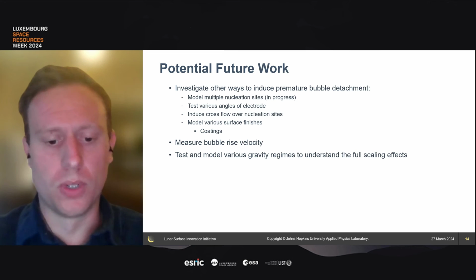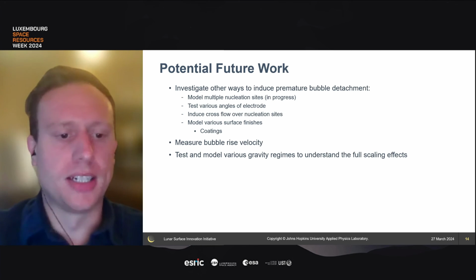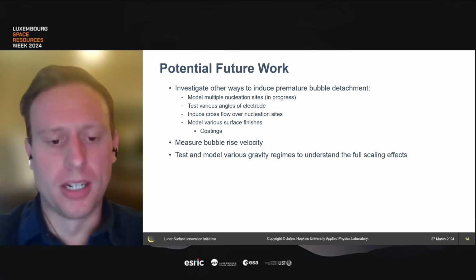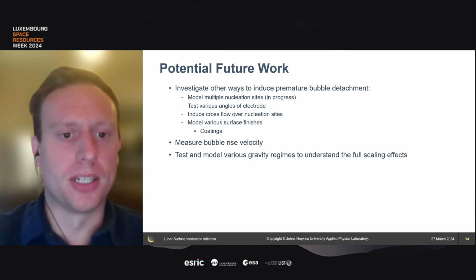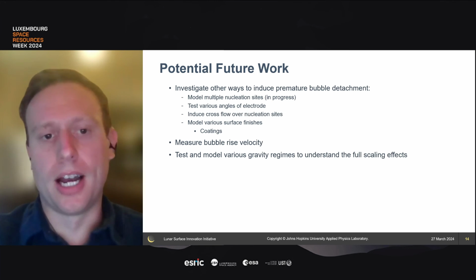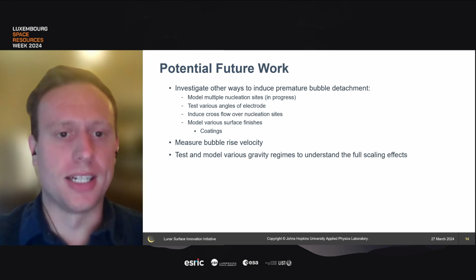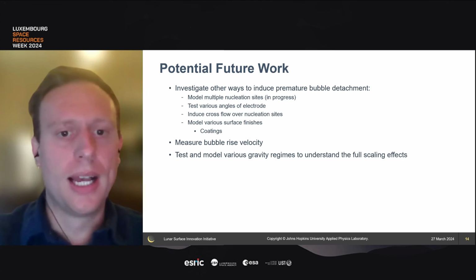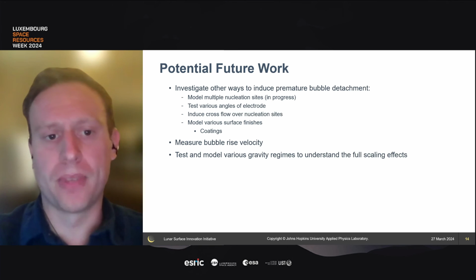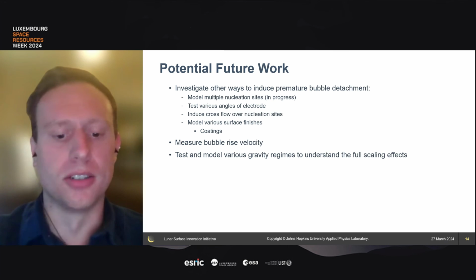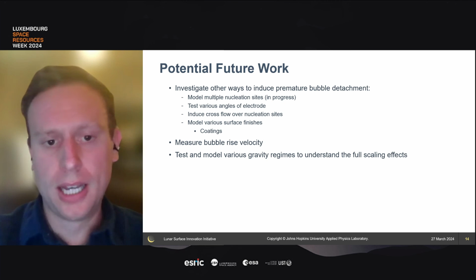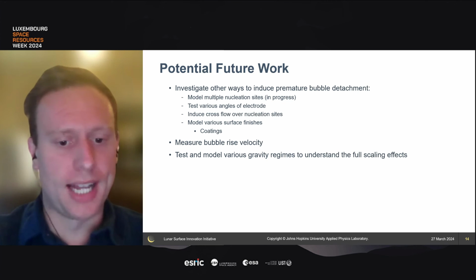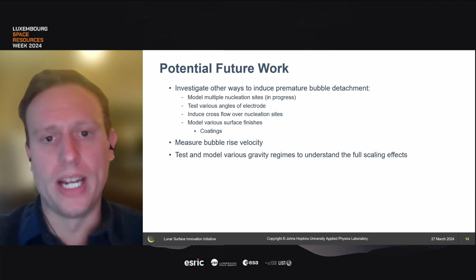So we'll start to model multiple nucleation sites. We've already started that, where bubble-to-bubble interactions may encourage early bubble detachment. And then other things, potential mitigation techniques such as crossflow, coatings to affect the surface finishes, and additional angles and orientations of the electrodes. But it's also important to note that while there may be ways to induce bubble detachment,